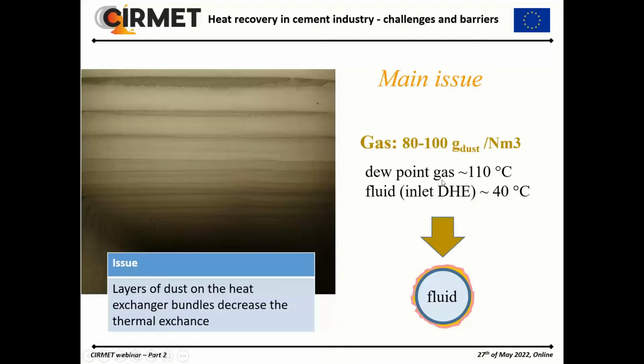About the barriers, the main problem we are facing is the high content of dust in the gases. We're talking about 80-100 grams of dust per normal cubic meter. As the dew point of the gas is more than 100 degrees, the inlet temperature of the working fluid is about 40 degrees. It happens that when the gases get in touch with the shell of the tubes,